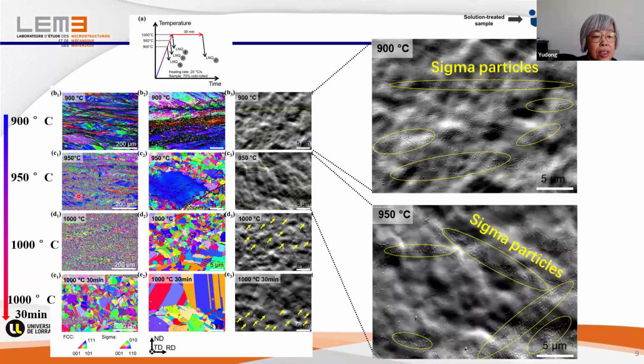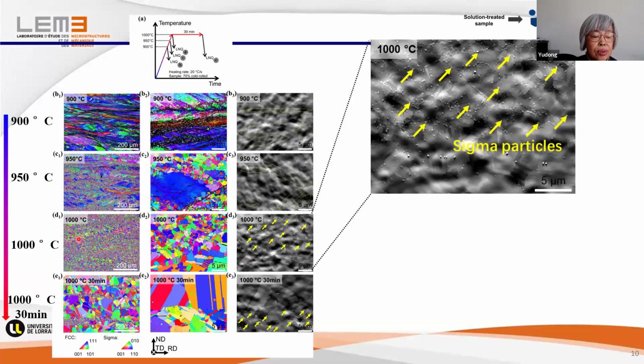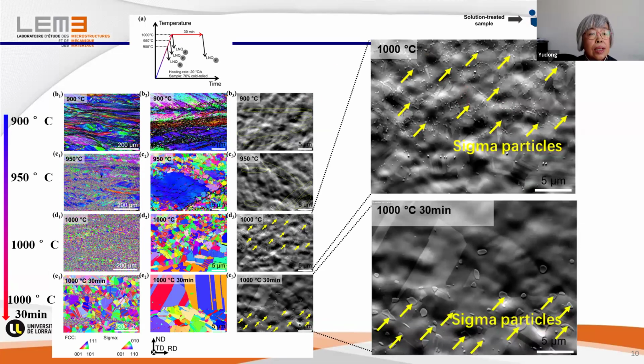And then when we increase the temperature, you see the microstructure is half recrystallized. And still, the formation of the sigma particles is not homogeneous everywhere, but mainly in the slip bands region. Then we continue to increase the temperature, and the material is fully recrystallized. We can see slight coarsening of the sigma particles. And now if we hold it for half an hour at this temperature, we have a secondary recrystallization. In some parts, the grains grow much more than in the part full of sigma particles.